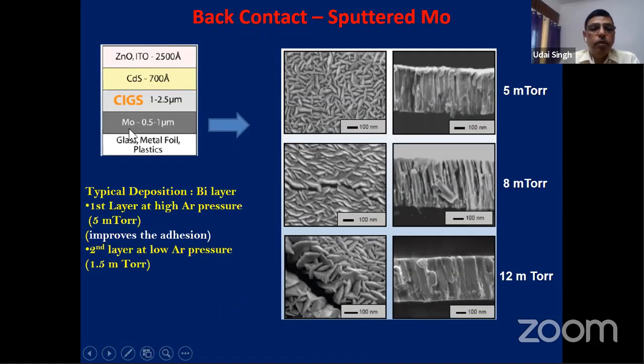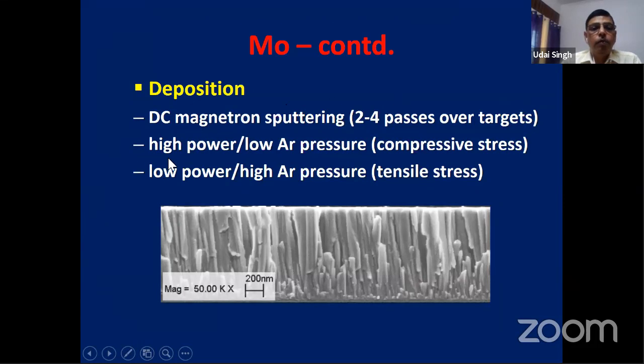So one can generally deposit a bilayer. Typical deposition is a bilayer. Why is a bilayer used? Generally they deposit the first layer at high argon pressure and the second layer at low argon pressure, to reduce the stress in the film. If you have a large stress in the film, it may peel off the substrate after a certain time. Deposition is generally done by DC magnetron sputtering, 2 to 4 passes over the target: high power with low argon pressure, and low power with high argon pressure. One will give you compressive stress, the other tensile stress. So you reduce the stress in the film, and your adhesion will be much better.